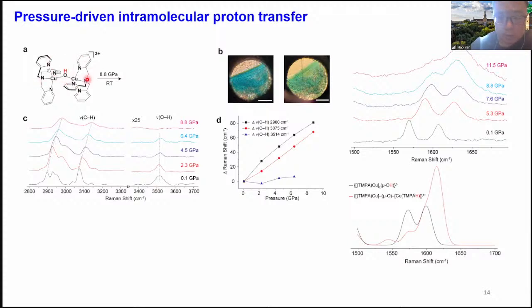The starting material is all symmetric. We put it under a pressure of about 8 to 9 gigapascal. What we have seen is that there's a color change going from blue to greenish.